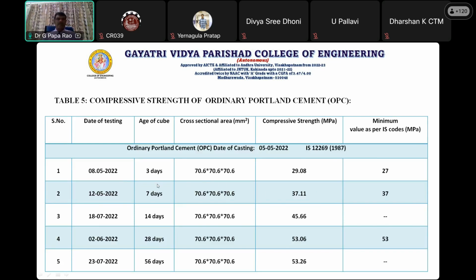We have cast the cubes with our standard size, 70 by 70 by 70 mm cube. As per the IS code, OPC 53 should get a minimum of 27 MPa at 3 days, 37 at 7 days, and 53 at 28 days. These are the strengths obtained with our laboratory tests. We got 29 MPa at 3 days, 37.11 MPa at 7 days, and 53.06 MPa at 28 days. Therefore, our cement is good, and we can proceed with further investigations with OPC 53 because it meets our Indian standard specifications.